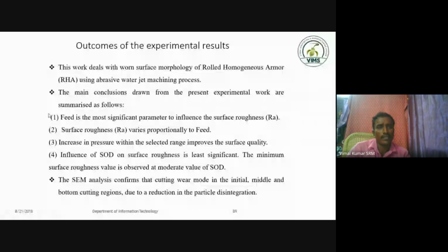This work deals with the surface morphology of rolled homogeneous armor using the abrasive water jet machining process. The main conclusions drawn from the present experimental work are summarized as follows. Feed is the most significant parameter to influence the surface roughness. Surface roughness varies proportionally to feed. Increase in pressure within the selected range improves the surface quality. The influence of SOD on surface roughness is least significant. The minimum surface roughness value is observed at a moderate value of SOD.